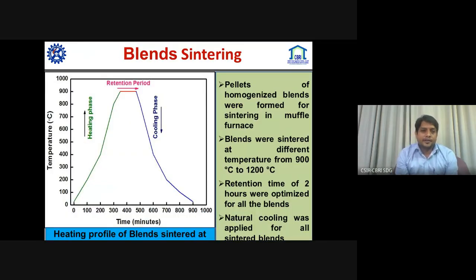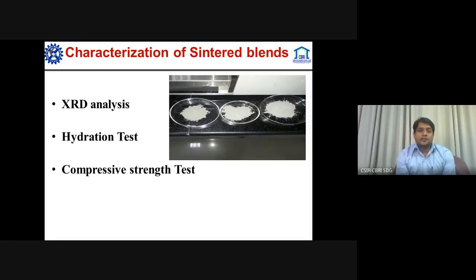And the retention period, heating profile of the blends: the pellets were formed with the homogenized blends and sintered in a muffle furnace. Blends were sintered at different temperature from 900 to 1200 degrees C. Retention time of 2 hours was optimized for all the blends. Natural cooling was applied for all sintered blends. And after that, the characterization of sintered blends was performed with XRD analysis, hydration test, compressive strength test.